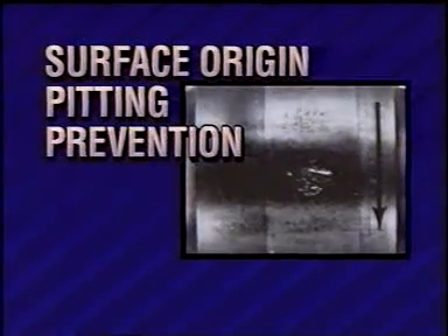With continued service, the crack progresses down into the metal a few thousandths of an inch. It spreads out on the surface until a small volume of metal has been surrounded by cracks. This cracked section soon falls out, leaving an arrowhead-shaped cavity or pit. This is a typical arrowhead-shaped pit in a test roller before it is destroyed by continued contact with the mating roller.